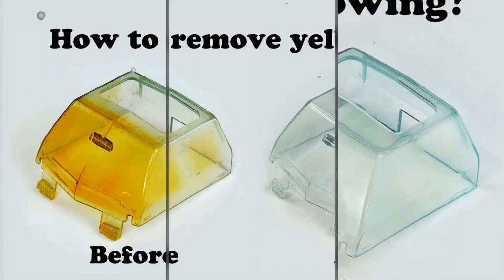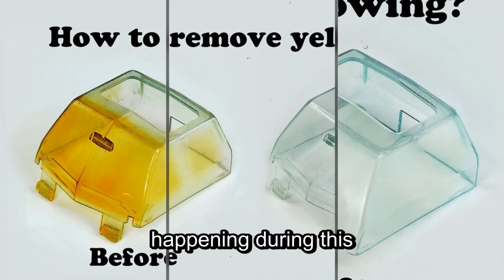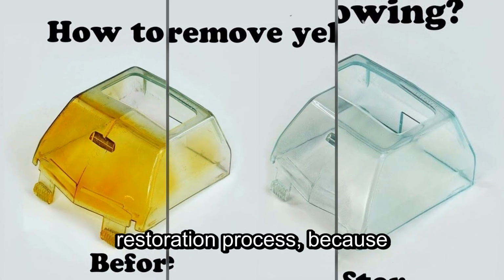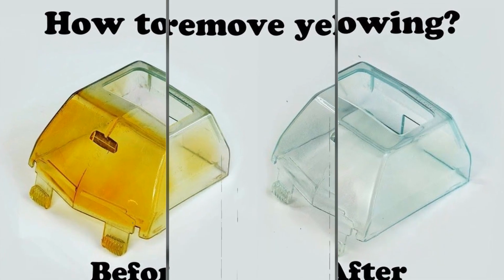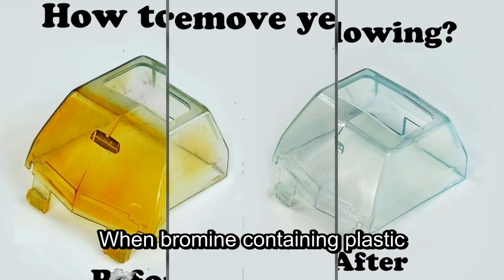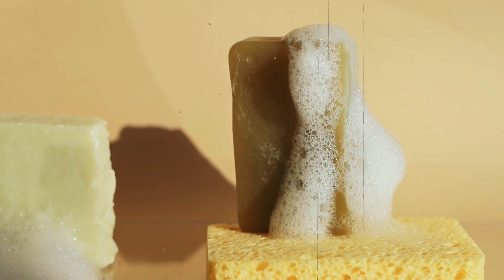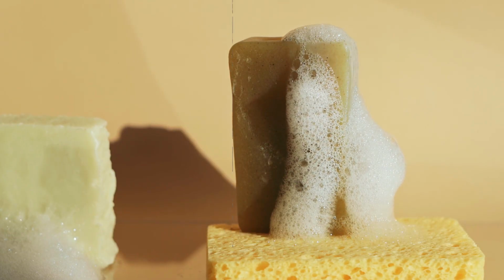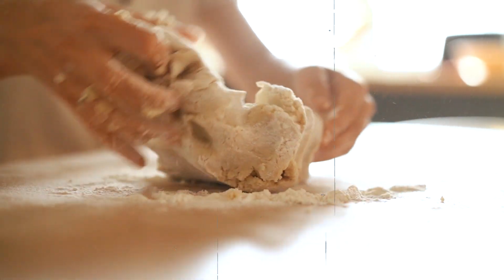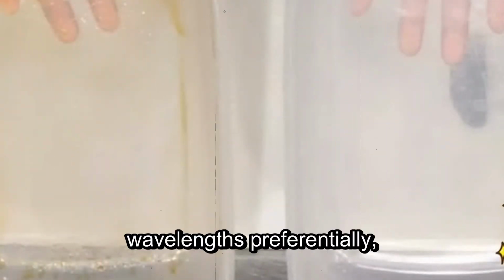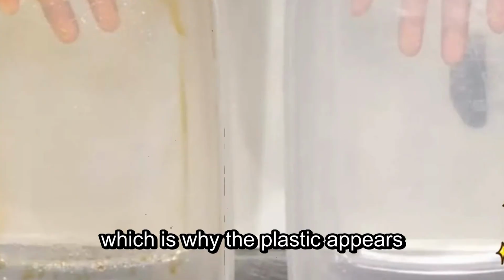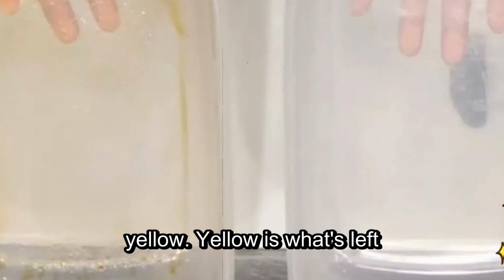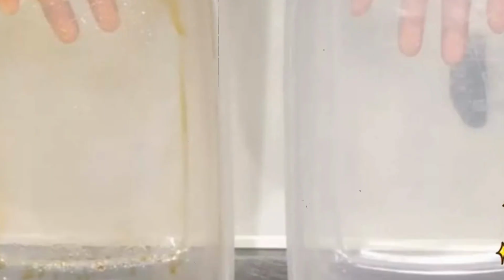Let's dig into the actual chemistry of what's happening during this restoration process, because understanding it will help you apply the technique correctly. When bromine-containing plastic oxidizes, the bromine atoms bond with oxygen from the air. This creates brominated organic compounds on the surface. These compounds absorb blue light wavelengths preferentially, which is why the plastic appears yellow. Yellow is what's left when you subtract blue from white light.